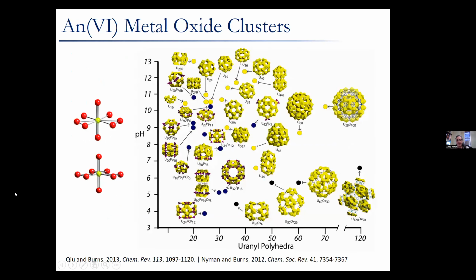So some of the prior work in the Actinide Center of Excellence was looking at metal oxide clusters that had actinides in the plus six oxidation state. And so the uranyl peroxide nanoclusters shown here on the screen are sort of the poster child. What you're seeing is a graph of the synthesis pH that the clusters are synthesized under as a function of the number of uranyl polyhedra.